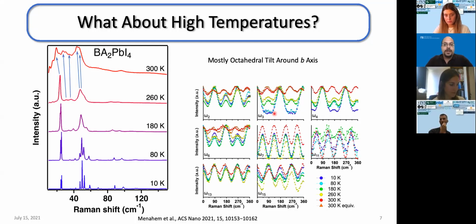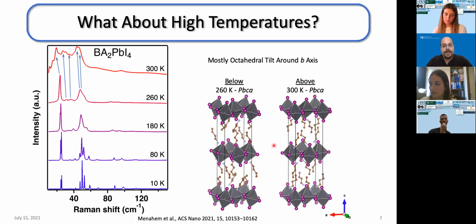Now, moreover, when I looked at the mode assignments done by DFPT, we saw that most of the modes persisting in the spectrum of the high temperature phase consist of an octahedral tilting motion around the crystallographic B axis. Now, if we go back to the XRD, we see that in the lead iodide layer, the most abrupt change, the most obvious change in the XRD, is the octahedral rotation around the B axis.